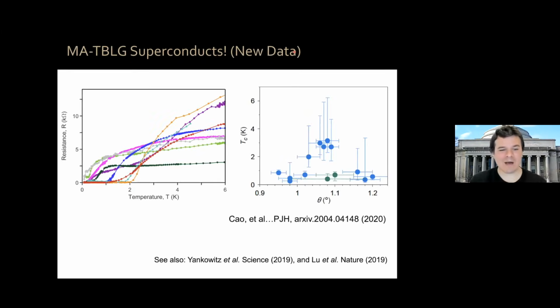Okay? So by now we have many devices. This slide is actually quite outdated already. We're beginning to measure the critical temperature as a function of angle. You see that there's sort of a dome in twist angle now, okay? And we've seen superconductivity roughly between 0.95 and 1.2, maybe 1.25 degrees, okay? So again, in a narrow angular range.